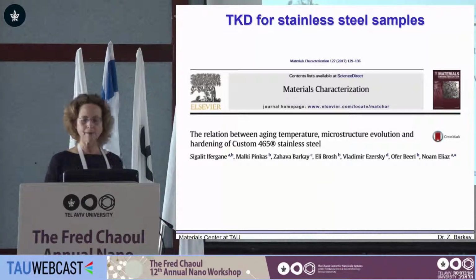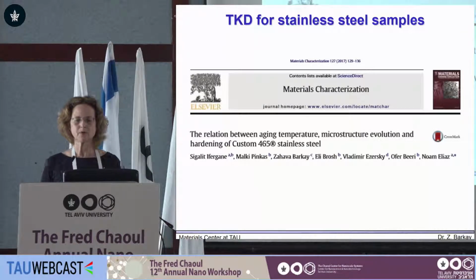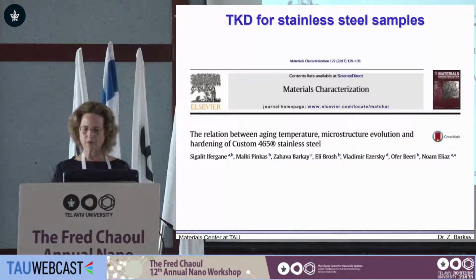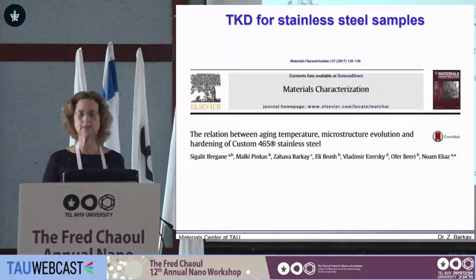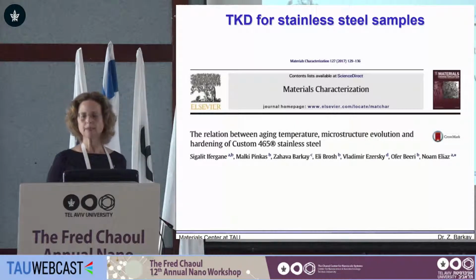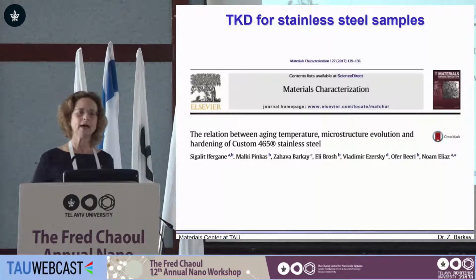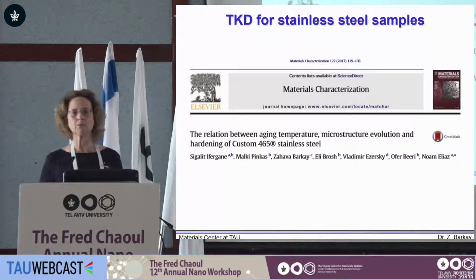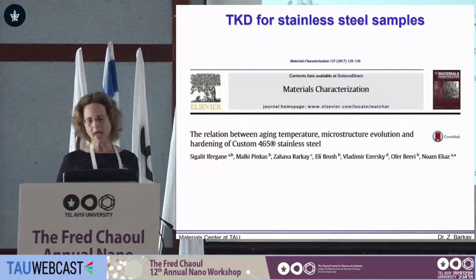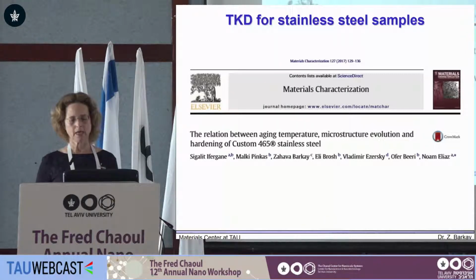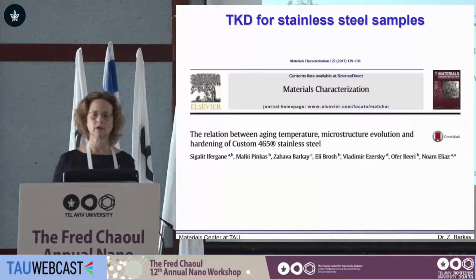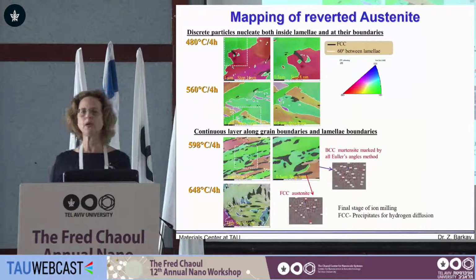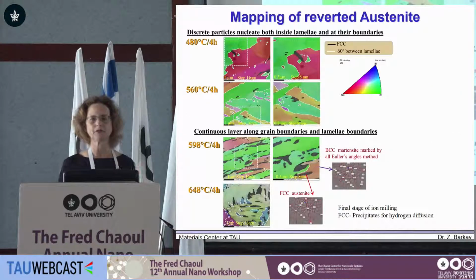The second example is for samples that were produced in the lab of Noam Eliaz by the student Sigalit Ifergan. She was preparing stainless steel samples and investigated the aging process on these samples relative to hydrogen diffusion and corrosion resistance. It was prepared by doing ion milling for thickness gradient.